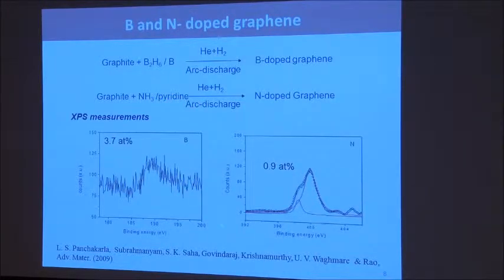Right away when you dope it, you introduce a gap. You get a small gap and semiconducting graphene, and with nitrogen-doped or boron-doped graphene, you have p-type or n-type graphene, and you can do that as well. So these are some of the things that were done.